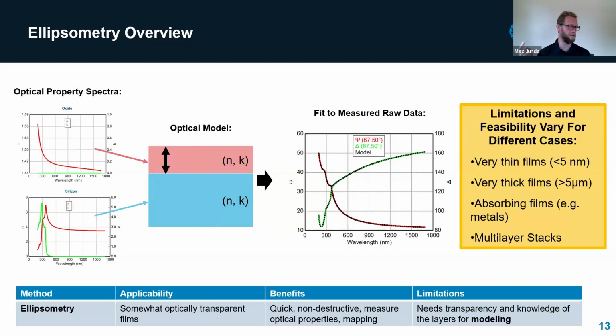And then we also have the thickness of any layers that are present. And so basically, in the most simple example, let's assume that we know what the optical properties for these materials are, this blue layer and this pink layer, as I've shown them here. So we know those spectra on the right, and those feed into the model, and we just don't know the thickness. And using these optical properties and hypothetical thicknesses for the layer, we can simulate what the polarization changes that we would measure would be.